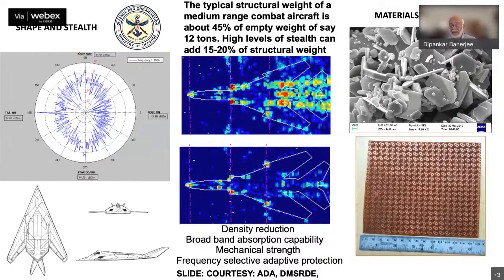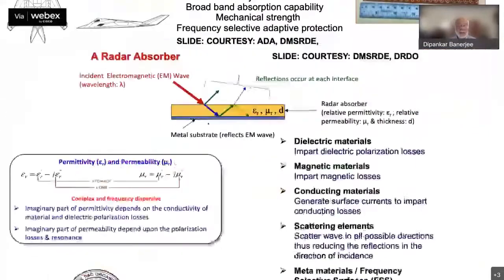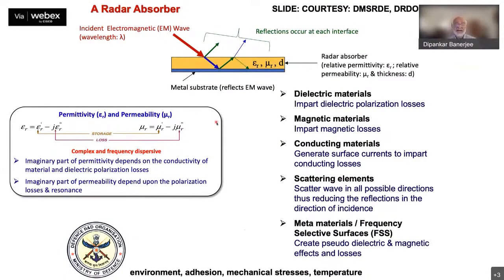And the varieties of materials that can be used in stealth applications are actually quite enormous, but they can also add to weight. So, for example, high levels of stealth can add 15 to 20% of structural weight. So the drivers for stealth are certainly density reduction, but beyond that, broadband absorption capability, mechanical strength, and perhaps frequency selective adaptive protection. And the physics of stealth materials is really determined by the physics of electromagnetic wave interaction with the materials. But while understanding the physics, one has to look at the environment, the adhesion of your stealth material to the airframe structure in response to mechanical stresses, temperature, and moisture as well. So the engineering of stealth materials and coatings into airframes is a whole new activity by itself, which we've been doing both in DRDO and at NAL now for quite some time.